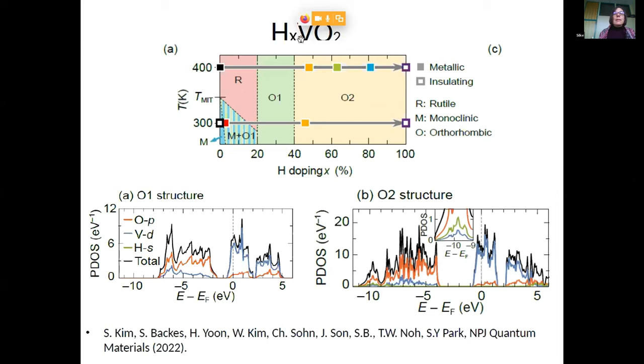So we can think of this HxVO2 to zero's approximation as a VO2 where we have actually added X electrons. And that means that we continuously go from a D1 configuration to a D2 configuration. Apart from that, the overall basic electronic structure is similar to what we had seen before. So we have an oxygen manifold here, and the T2G states that we have already studied in the pristine compound, but which here now are filled with 2 electrons. Okay, so 2 electrons, that is not insulating in the previous picture.